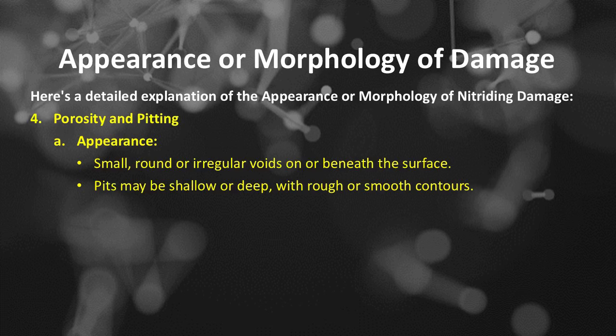Number 4 of the appearance or morphology of nitriding damage is porosity and pitting. The appearance would be small, round or irregular voids on or beneath the surface. Pits may be shallow or deep, with rough or smooth contours.